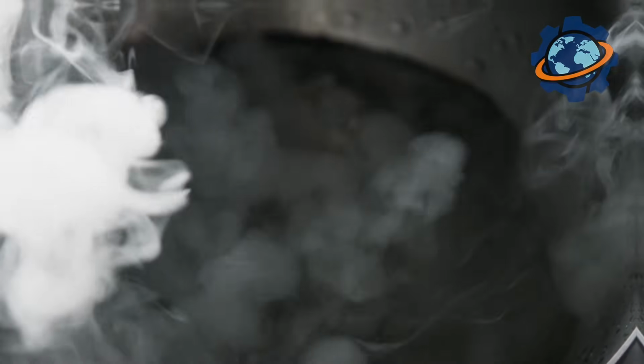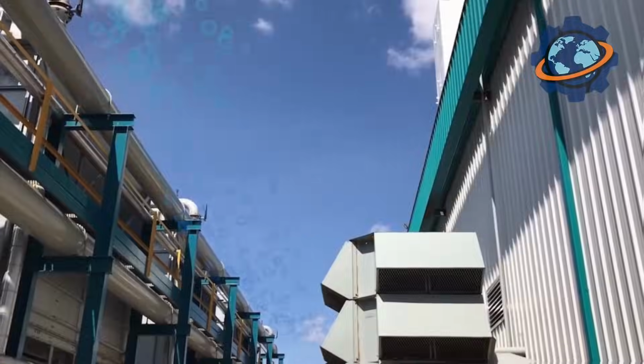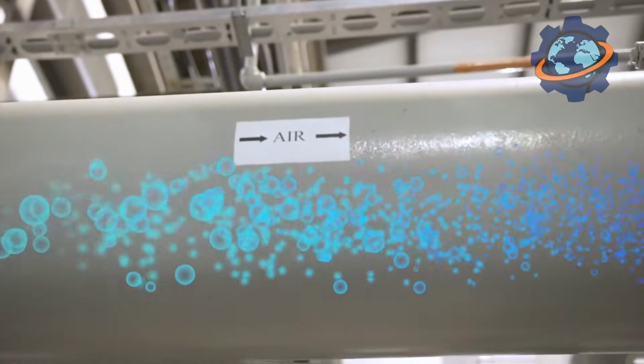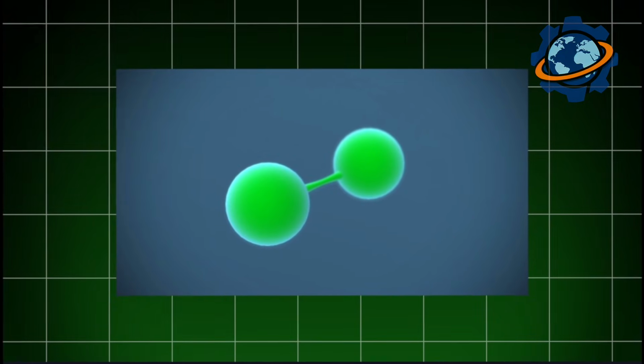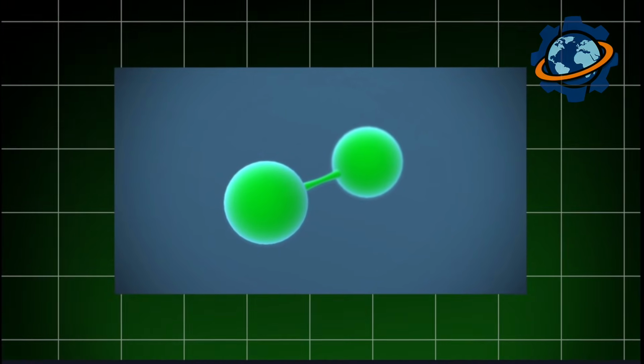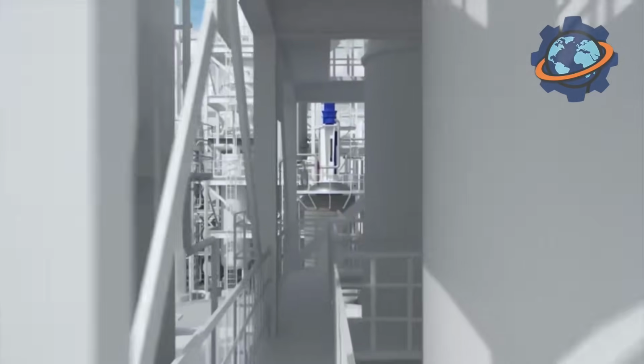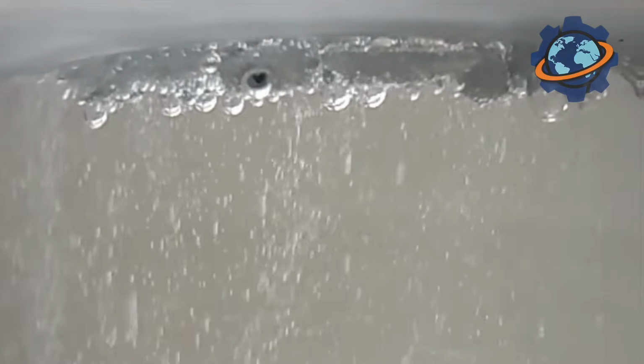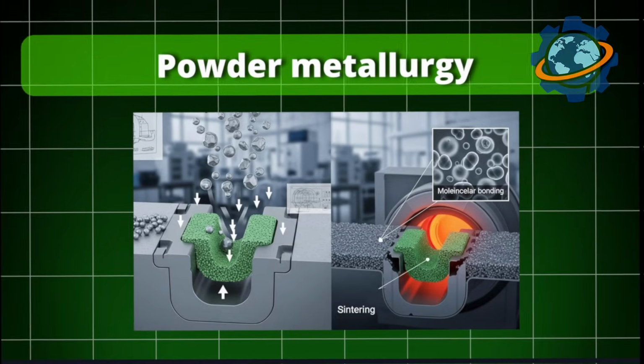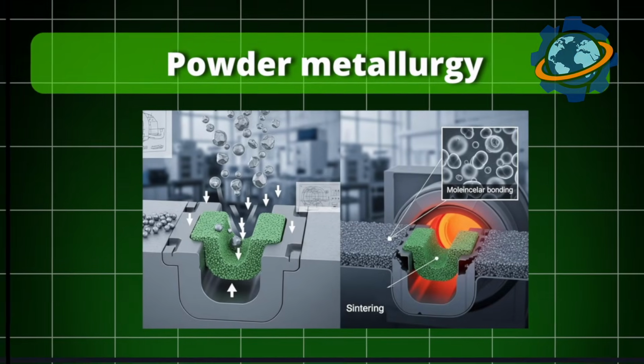Inside tube furnaces heated to 1,800 degrees, hydrogen gas flows over tungsten trioxide. The hydrogen strips oxygen atoms, leaving metallic tungsten powder. But here's the challenge. Pure tungsten powder is useless. The particles don't bond. Press them together and they crumble. Tungsten's ultra-high melting point makes conventional melting impossible. No crucible survives temperatures required. The solution? Powder metallurgy.